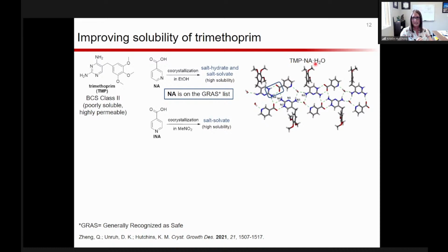And so this is the nicotinic acid with water. And so you can see this is sort of the main interaction between the two components. So this is the trimethoprim, the big molecule here, and then the nicotinic acid. So they interact sort of via a 2-point hydrogen bond. And you can see the acid is deprotonated and the hydrogen now resides on the ring of trimethoprim. So you can see it didn't used to have a hydrogen, but that's where the proton transfer happens. And then the pyridyl nitrogen is actually hydrogen bonding with water, which was crystallizing the lattice as well.